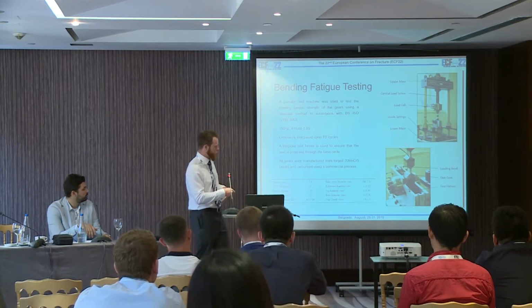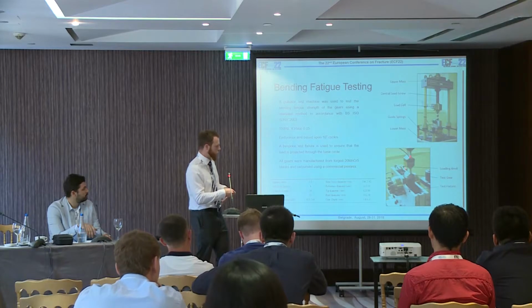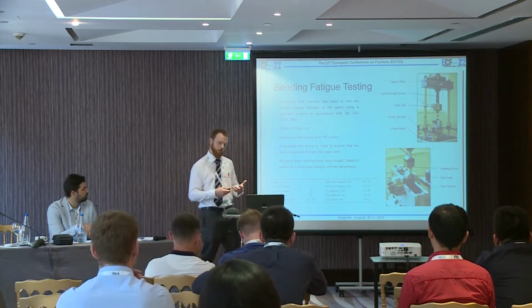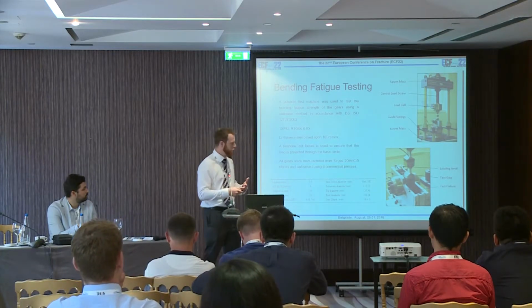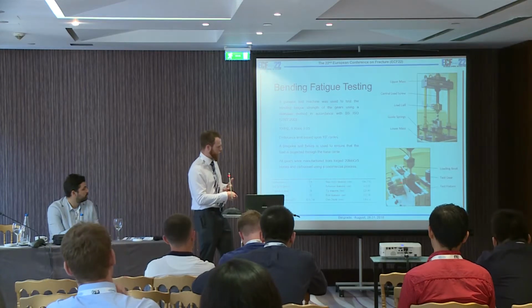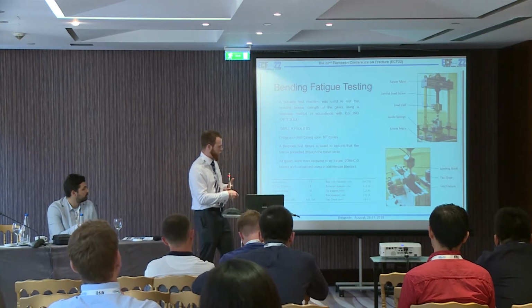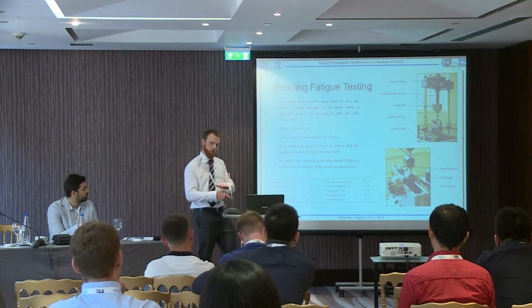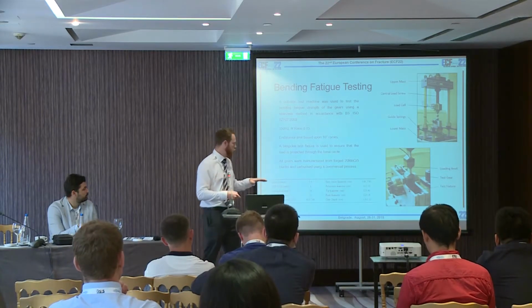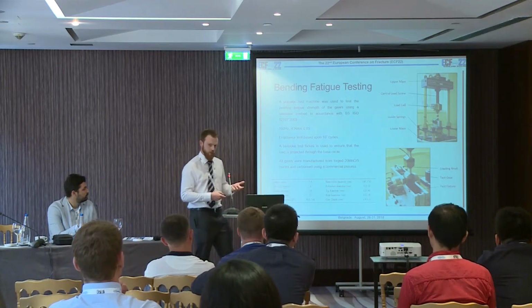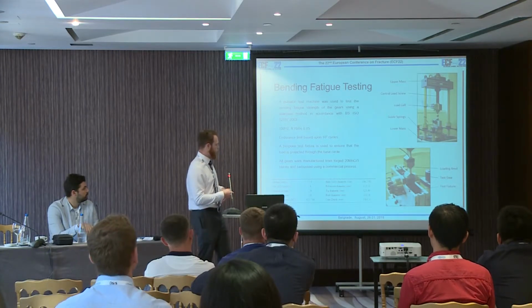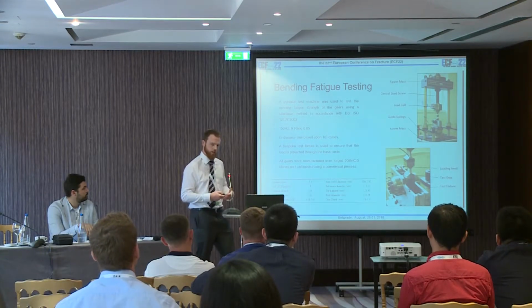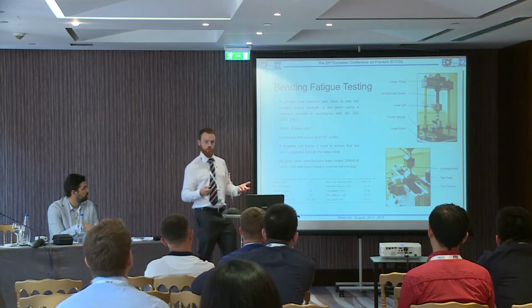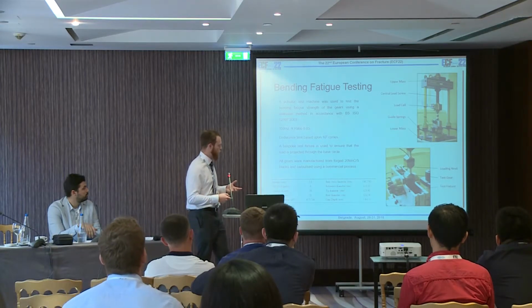We also make sure that we have this custom loading anvil, which makes sure that we're representing the line contact you would see during operation, and that we're not introducing load distributions which are predominantly towards one side, so we want it to be nice and even across the tooth. We use an endurance limit of 10 to the 7 cycles, and we can do that because these machines will operate at 150 hertz, so we can generate a large number of cycles over a relatively small period of time.